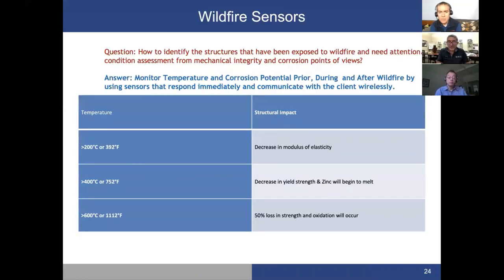So give us an example, if you could, what ends up happening with regards to the specific temperatures and the mechanical properties? What happens as we go through a wildfire and you get to these varying degrees? Well, as I mentioned before, there are three regions of temperatures that you have to be concerned about. Greater than 200 degrees C, greater than 400 degrees C, and greater than 600 degrees C. The critical temperature, obviously 600 degrees C, means you already have lost 50% of strength and oxidation will also take place. At 400 degrees C, you start to have the melting temperature.